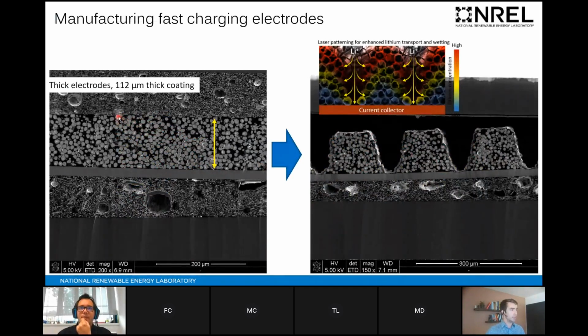This is an NMC electrode. We see the particles. This is 112 micrometers thick. We see that this is placed on the current collector at the bottom here. This fibrous material is just part of the sample preparation technique, so it's only the particles on the current collector that's important here. And this is before laser ablation, and then we use laser ablation to introduce these highways that I showed in this illustration to alleviate the lithium concentration gradients.